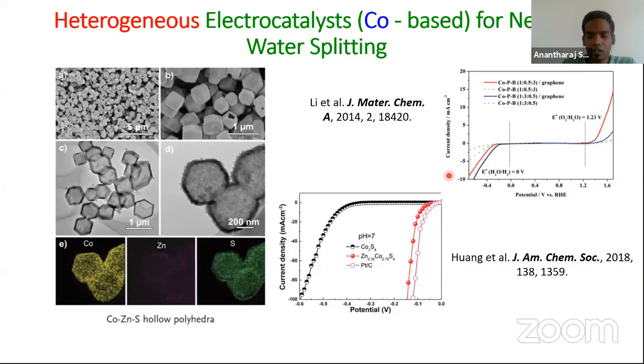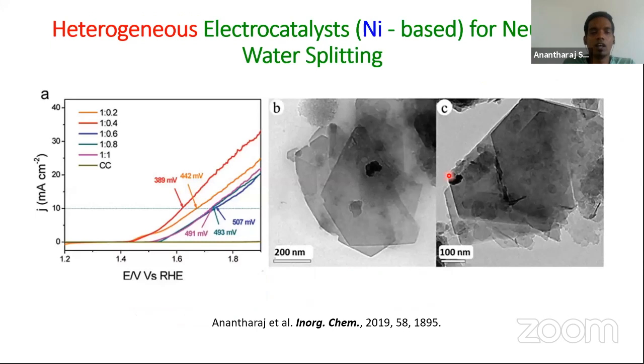So you can actually make it the way in which you want to work it. These are an example for cobalt-based heterogeneous electrocatalyst for neutral water splitting. And we also did some work on this area. This is one of our nickel-based electrocatalysts where we prepared nickel iron hydroxycarbonate, which is similar to NiFe LDH material,